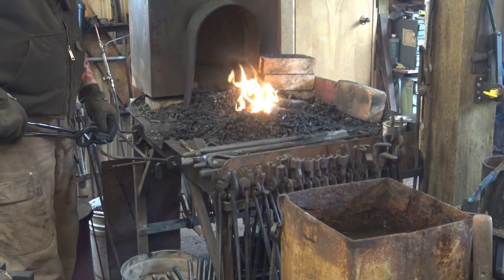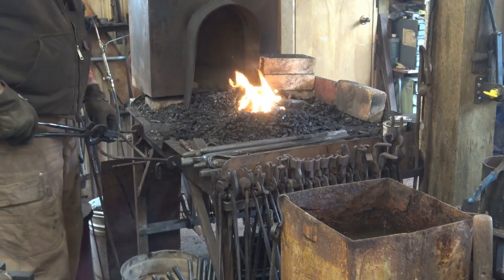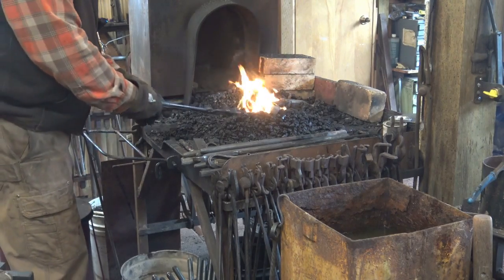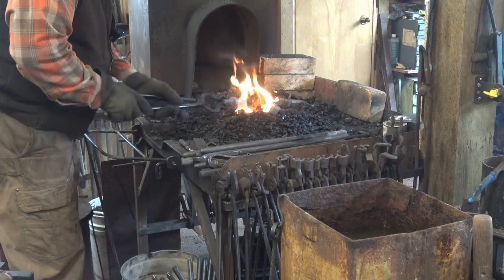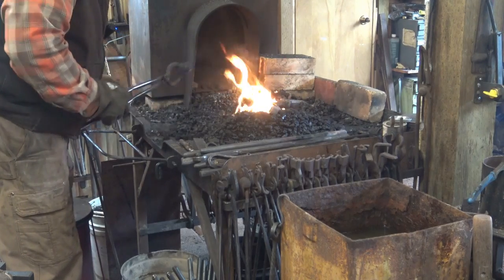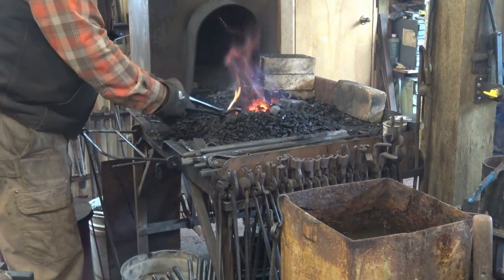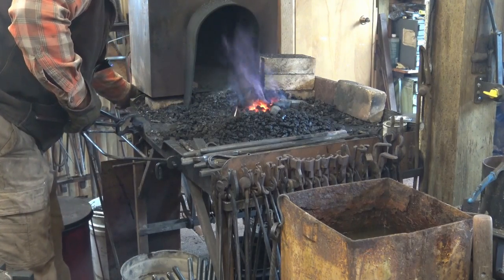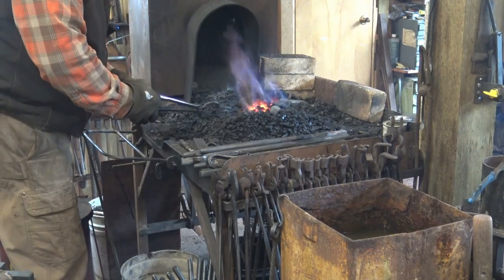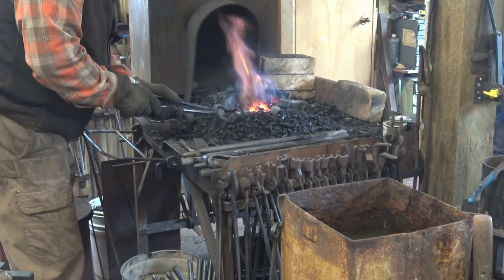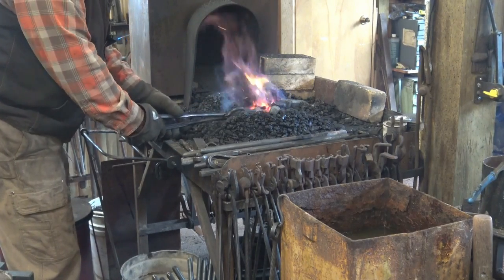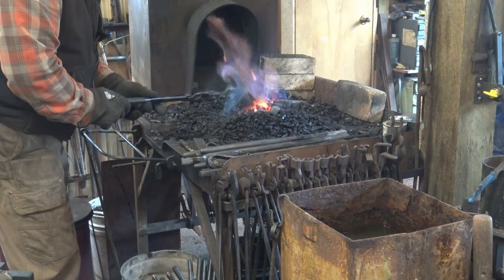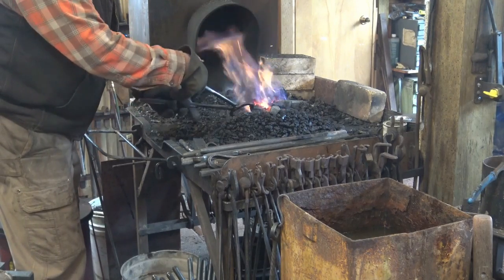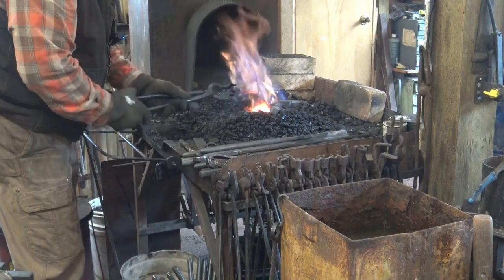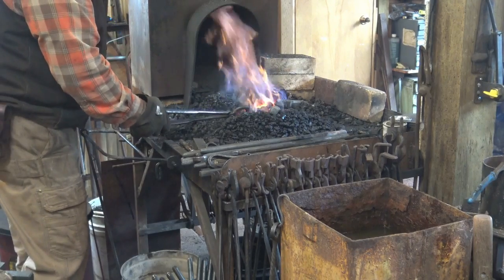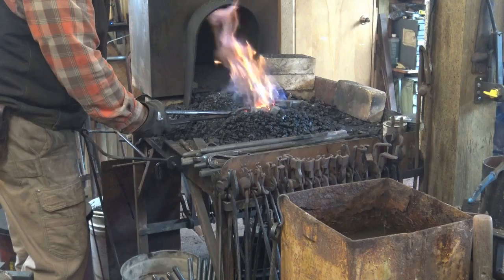Unfortunately, these are not simple carbon steel, so it's not 100% accurate. These need to be a little bit hotter than that. So I'm going to bring this up just a little bit more, and turn that blower down quite a bit. And you really only need to harden the last inch or so, but you need a nice even heat. If there's a sharp transition between hot and cold, you're going to crack it. And the same thing goes for when you quench it.